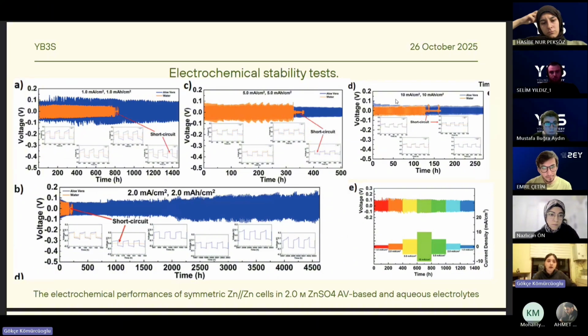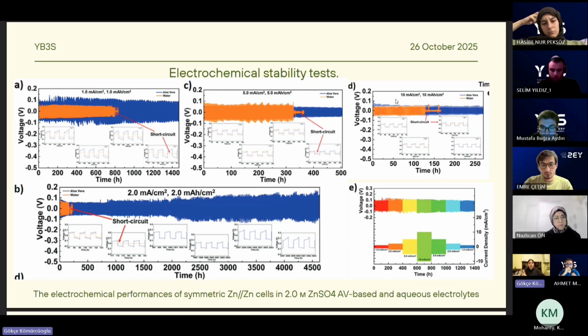For electrochemical stability, they made various tests in this field, and in different current densities. The most successful test of them all is with 2 milliampere per centimeter square, and in this test we see that aloe vera cycled more than 4,500 hours, which is showing great stability.